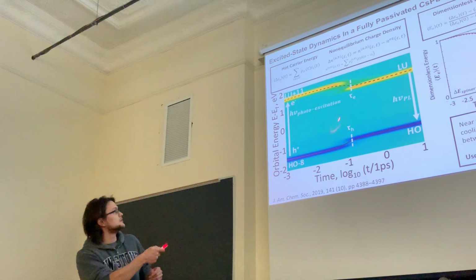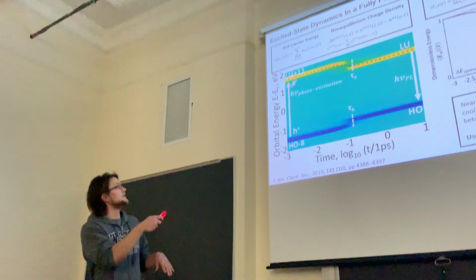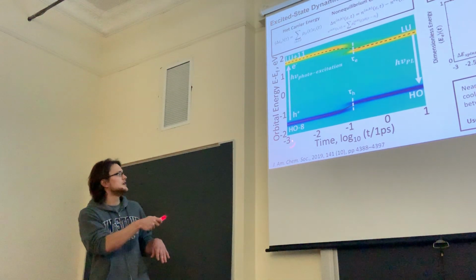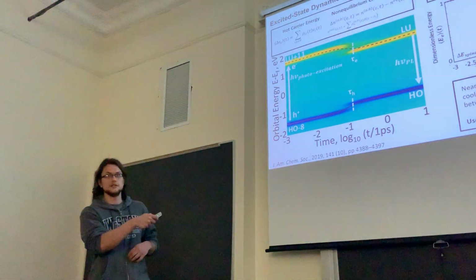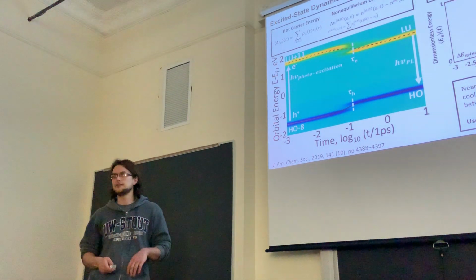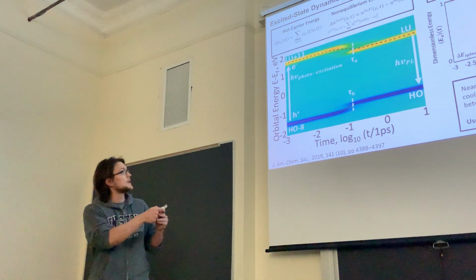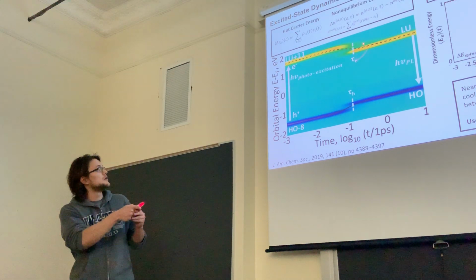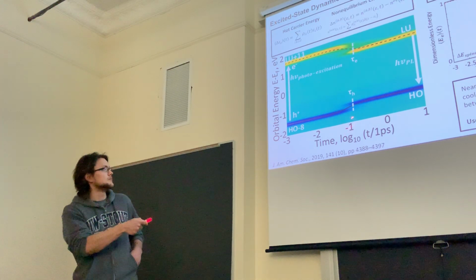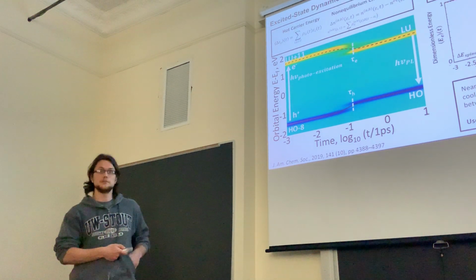The green represents charge neutral background, so just ground state. The yellow represents non-equilibrium charge density, so you have a photoexcited electron, and blue represents hole density at these energy states, and the lines just correspond to energy expectation values due to changes in population over time. And so for both these models, we see fairly fast hole cooling. It occurs on 100 femtosecond time scales, and that's in line with what they see in experiment.